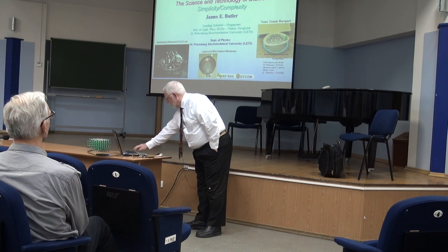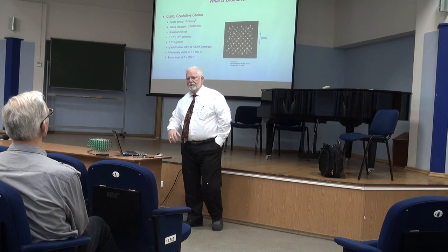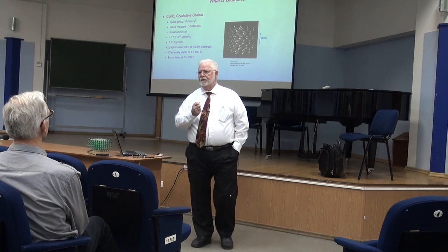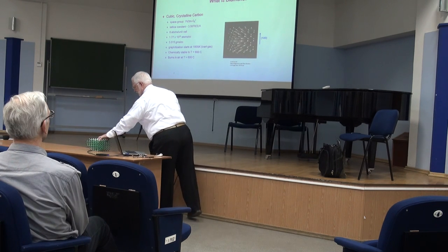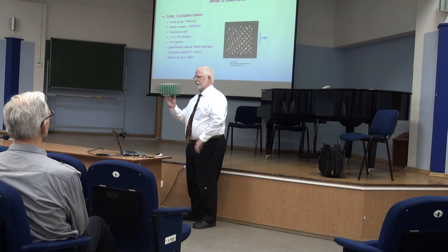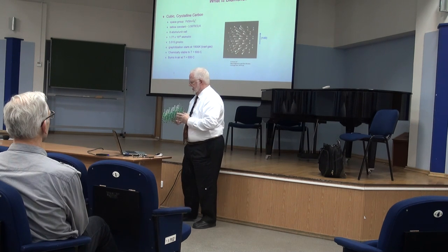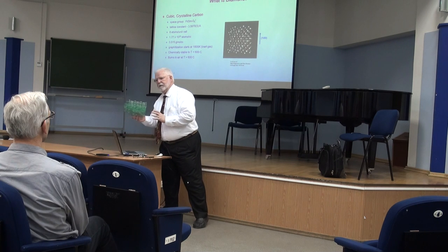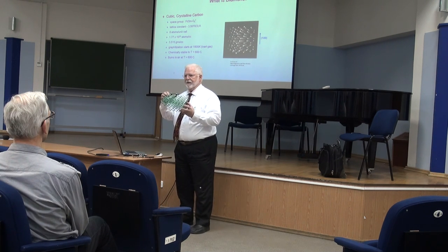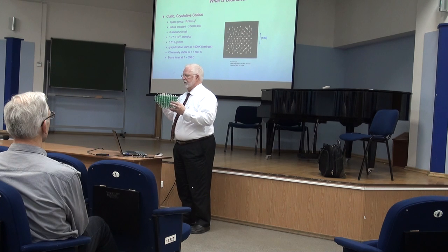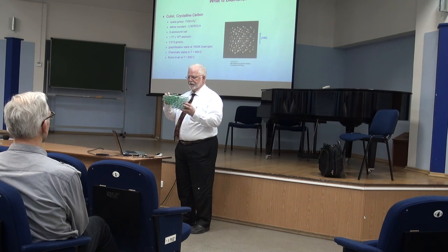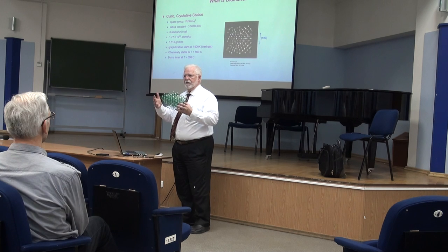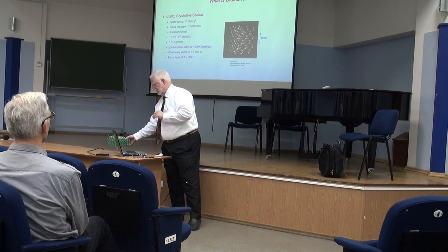Okay, what is diamond? Diamond is nothing more than crystalline carbon in the cubic form. And I show here the lattice of diamond rotating about the 100 direction. What's unique about diamond is it has more atoms per unit volume than any other terrestrial material. And when you couple that to the strong carbon-carbon bonds in diamond, you can derive almost all of the material parameters that make us interested in diamond.